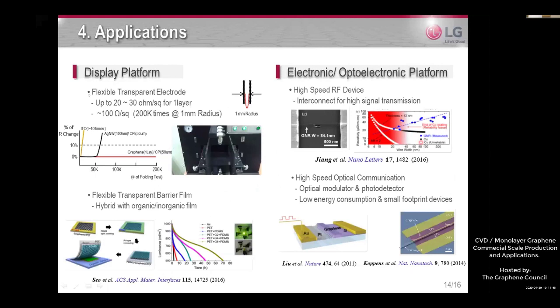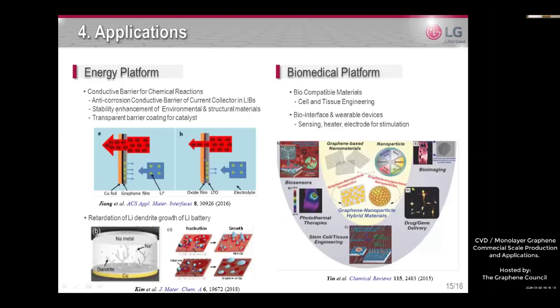We tested the flexible transparent electrode. We did a folding test. Only CVD graphene survived 200K times folding with a 1 millimeter radius. So we believe it can be used in new form factor displays. Graphene can also be used in the energy platform, as a conductive barrier for chemical reactions, and for the biomedical platform.